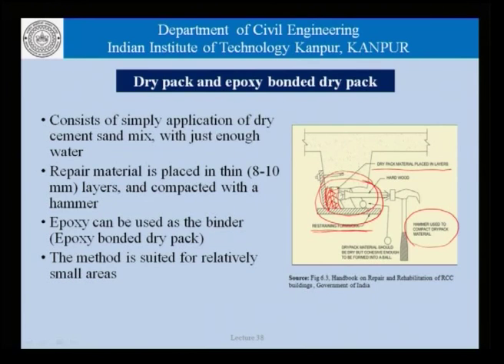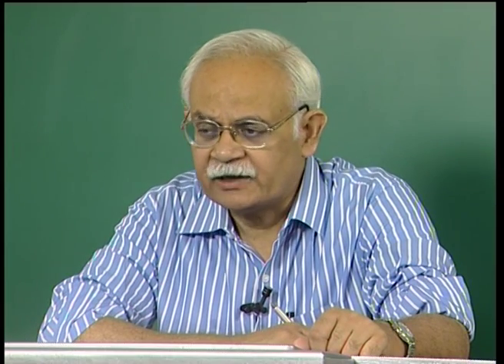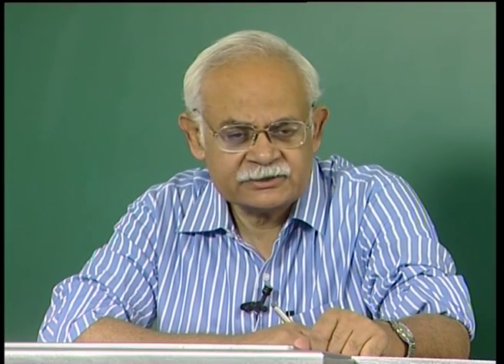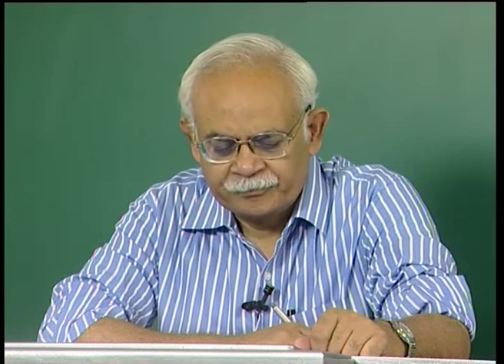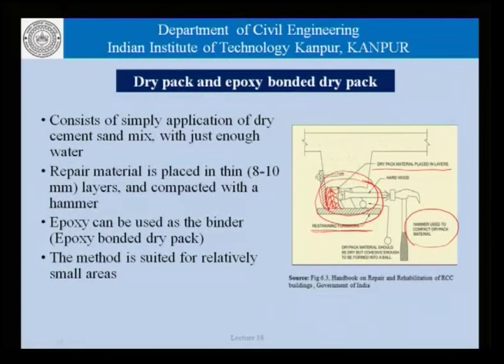material. Now, this material could consist of a cement sand mix, which is basically cement mortar with just enough water. So, it is basically a very dry mix, because the compaction that we are doing is with a hammer, and that we can obviously do only if the mix is dry. And as we said, the repair material is placed in thin layers and compacted with a hammer.